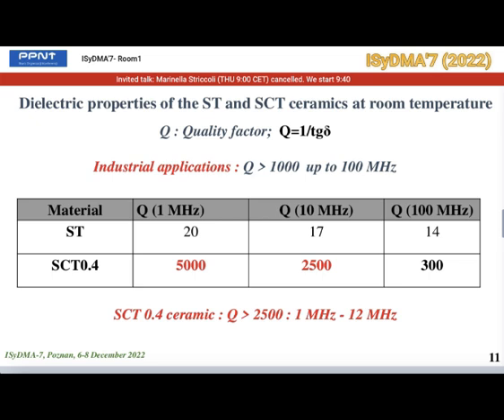Now, the quality factor is defined by Q equals 1 over tangent delta. Generally, for industrial applications, high quality factor ceramic capacitors must exhibit Q values higher than 1000 for frequencies up to 100 megahertz, or higher than 200 for frequencies ranging from 100 megahertz to 1 gigahertz. For our sample, we can see that SCT gives Q values higher than 2500 from 1 to 12 megahertz.